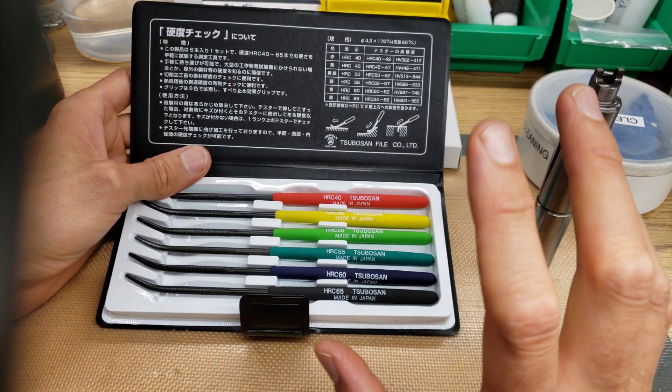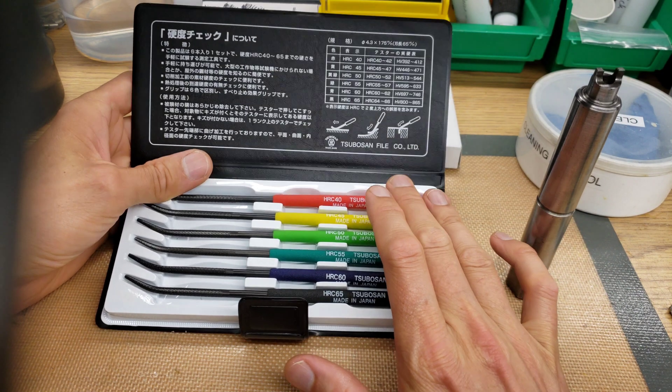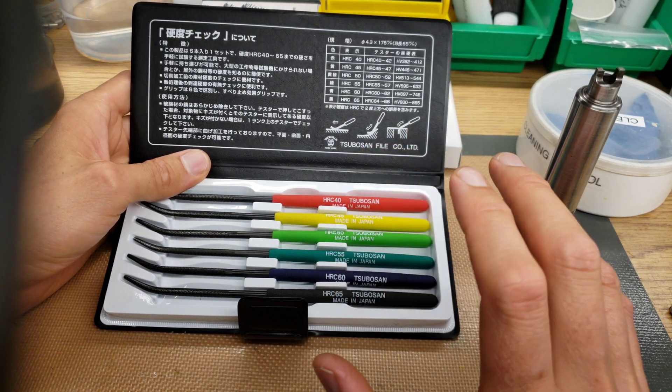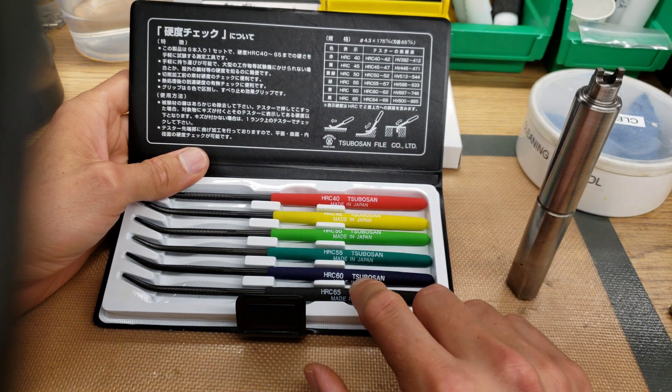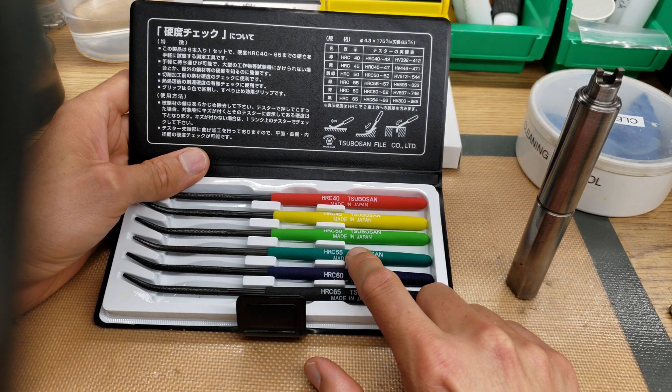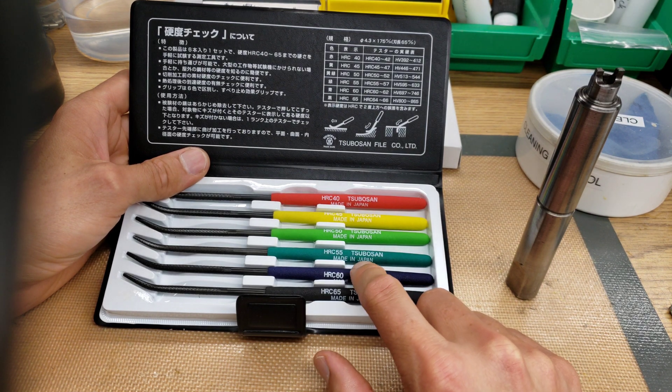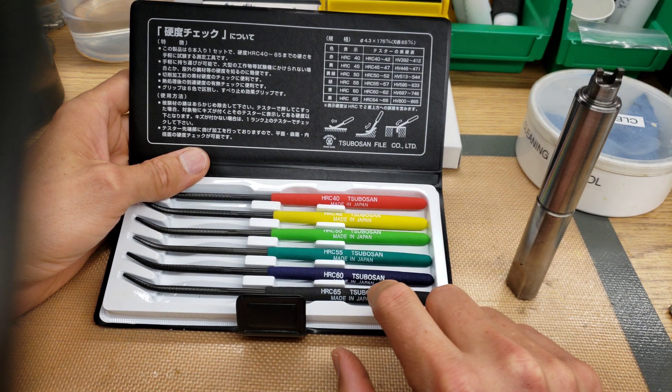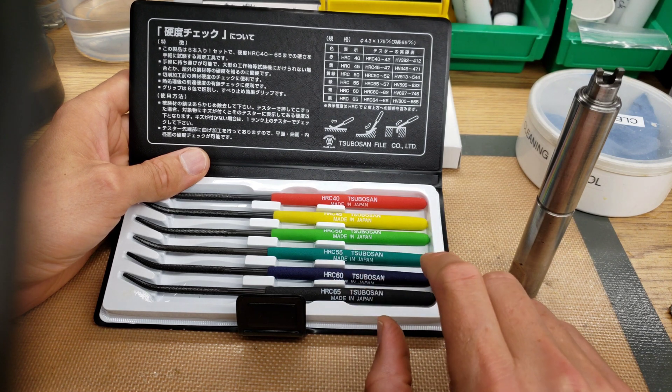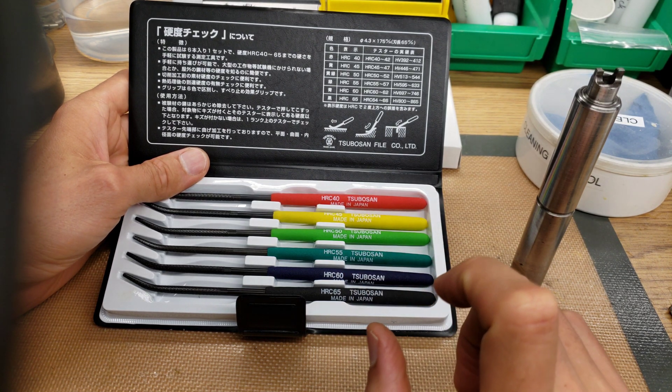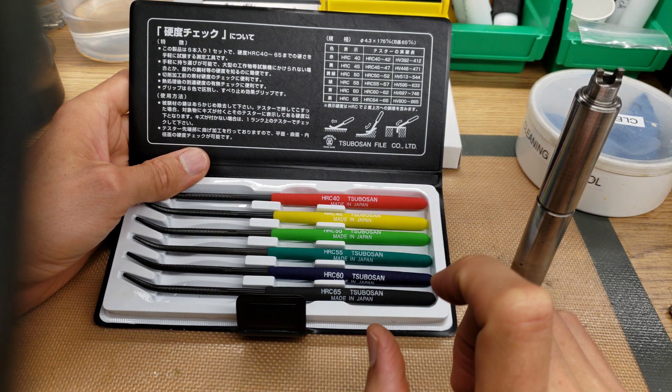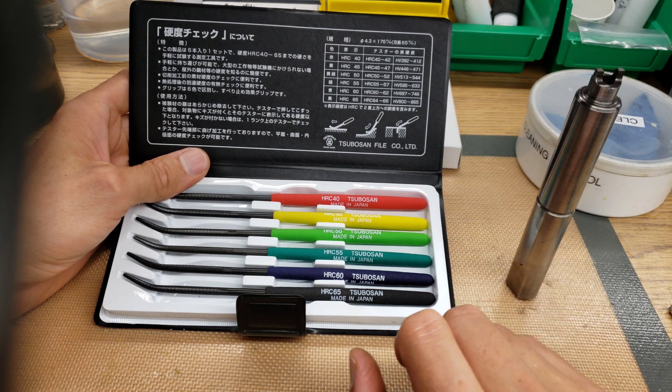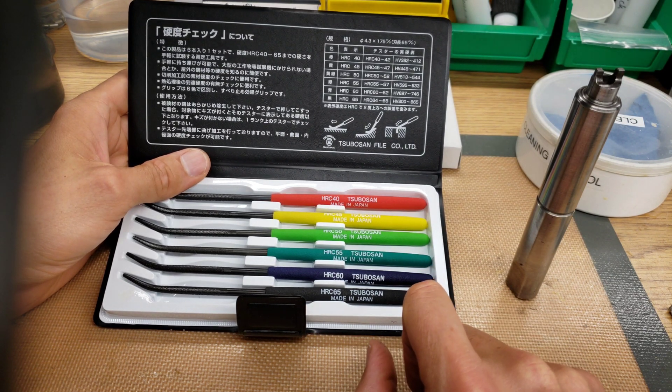Even though the range is up by fives, it's perfectly fine for our use to know approximately where it is. And you can actually tell whether it's on the low side or the high side. So you can make a pretty educated guess within I would say plus or minus two to three HRC where the hardness is.